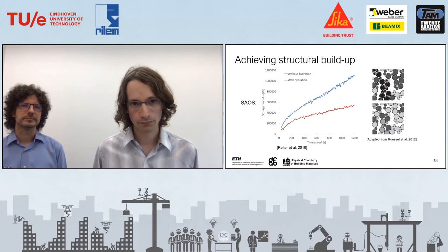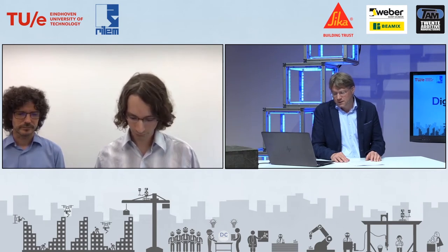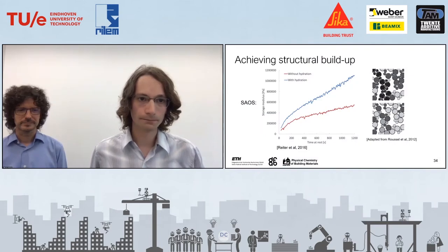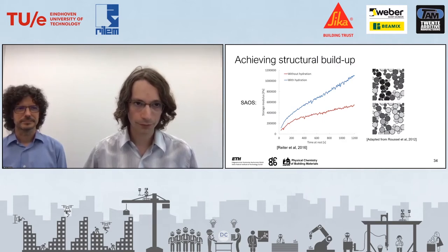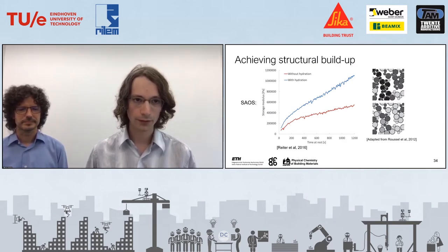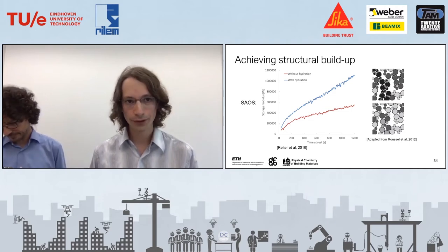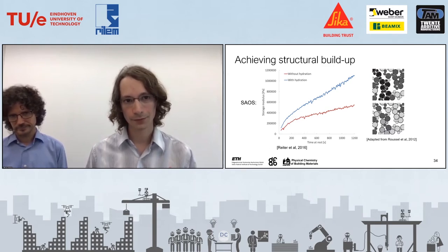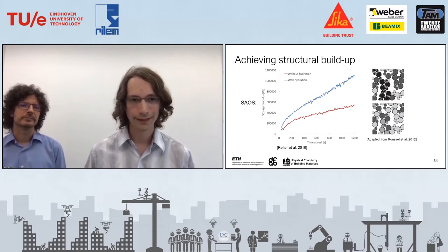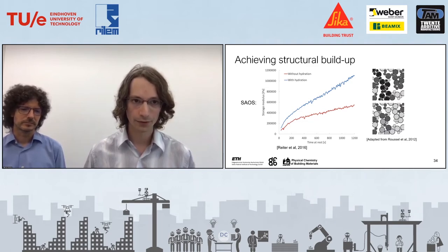Okay. And another question we got on this same test is, De Bradery Somme is asking if this penetrometer test can be an easy replacement for yield stress measurements in a rheometer. The target of the penetration test is really ease of use, because if you want to do static yield stress measurements in a rheometer, the way to do it is with a vane test. And that means placing the sample in advance, letting it rest until you want to do the measurement. And that means that you usually only get one measurement point every time that you are mixing a material.